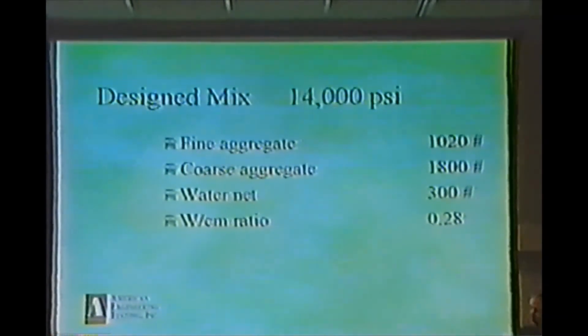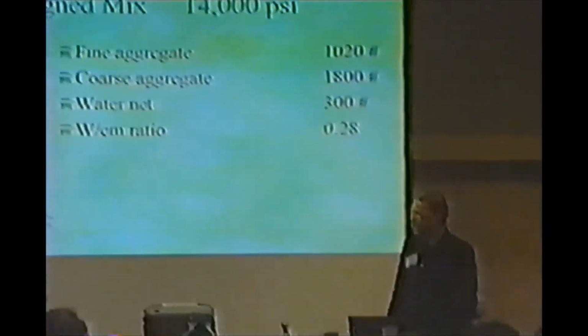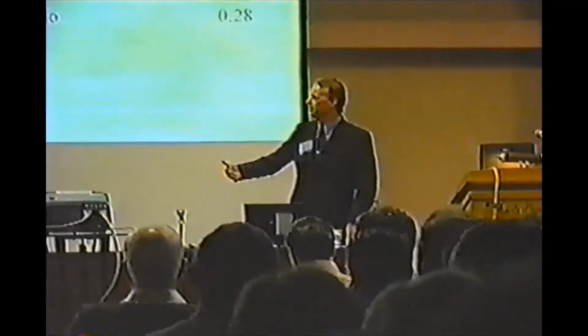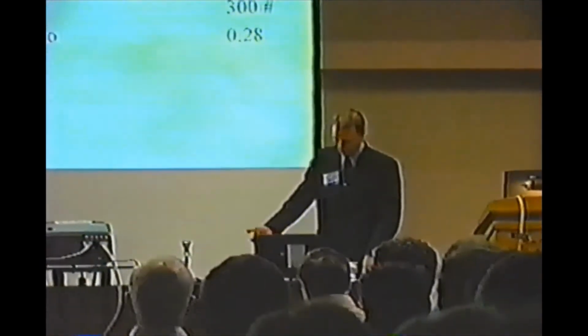You can imagine mixed with a 0.28 water cement ratio, how do we even get that out of the truck? The only way we can accomplish that is with those 4.5 gallons of the admixtures. So again, reviewing that mix, you have cementitious materials over 1,000 pounds. You have the admixtures of 4.5 gallons, and then the aggregates with that water cement ratio of 0.28.